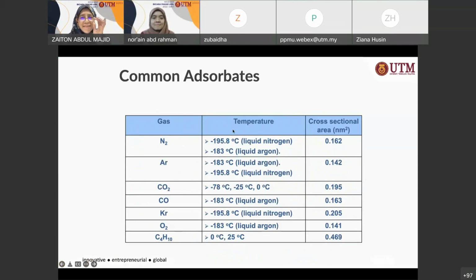Okay. So these are the common adsorbates that we use here in physisorption analysis: nitrogen, argon, carbon dioxide, krypton, oxygen, and also butane. If you look at the cross-sectional area, just now when I looked at the formula for specific surface area, I used the cross-sectional area 0.162 because I'm using nitrogen. So you can use the same formula, but just replace the cross-sectional area with that of the adsorbate gas that you are looking at. Otherwise, if you are still using nitrogen, you can still use that 4.35 times Vm.